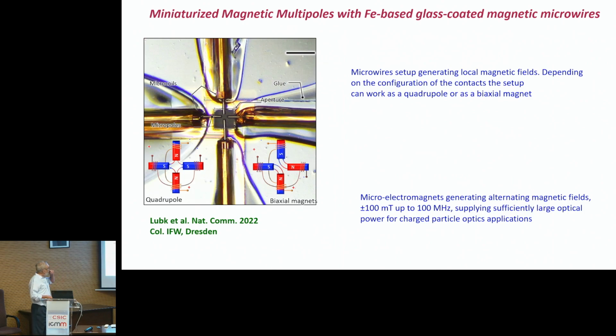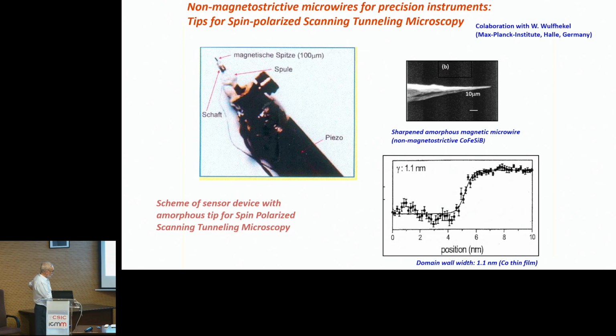Another application, very recent: we supply these microwires to the people in Dresden. They are interested in generating, very locally, a strong gradient magnetic field. So we have 4 microwires, with some coils at the end, to generate a single domain structure in each one. Depending on the coupling of the different magnetic fields, we can get quadrupole or biaxial magnetic fields just in the very center of this disposition, which is used by these people for very attractive applications.